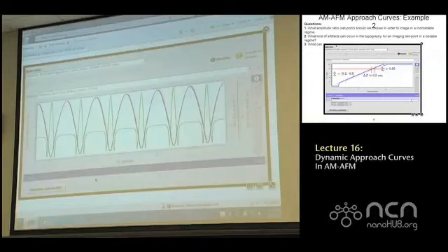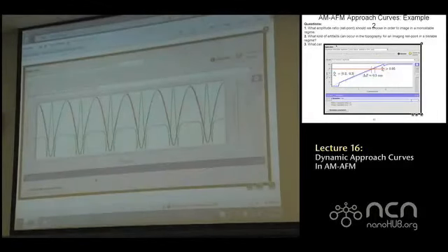But occasionally, under experimental conditions, we might have a hysteretic force, in which case one of the peak attractive forces will look a little bit different from the other one because of some hysteresis and adhesion and so forth. But this is characteristic of what we will see in most tapping mode AFM experiments if we were able to look at the tip-sample interaction waveform. Okay?